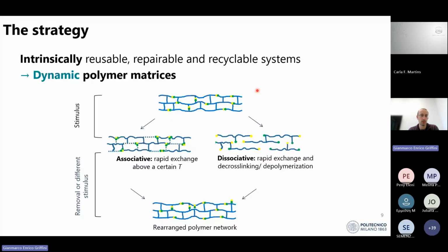On the one hand, we have what we call the associative systems, where we have a sort of permanent cross-linked network that can undergo bond shifting or bond exchanges during thermal treatment, typically in the presence or in the absence of catalysts. And this enables macromolecular movement that then leads to the possibility of reprocessing the material.